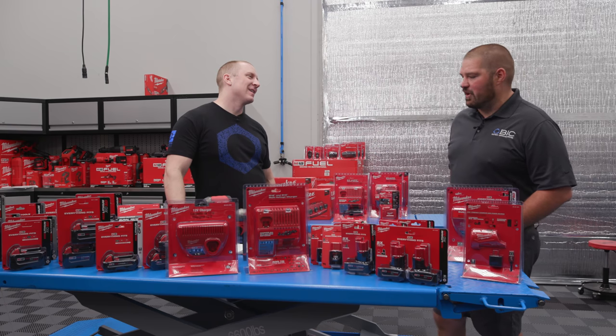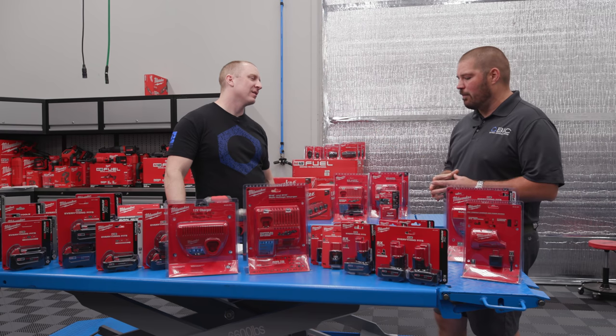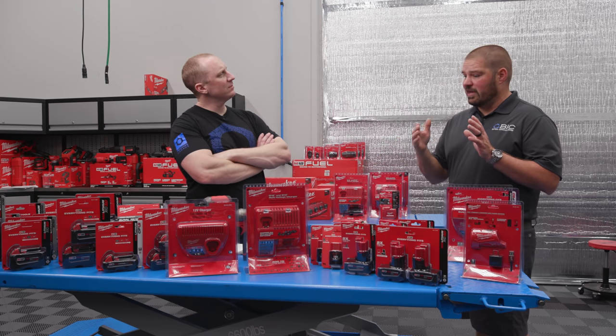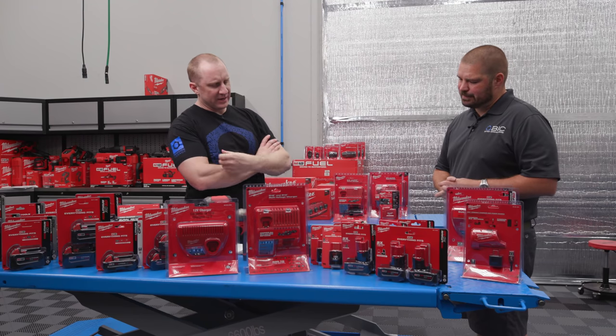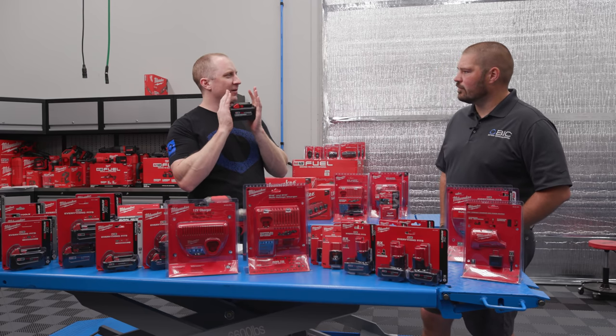Being up at the upper 100% is actually bad — it's better to stay around 30–70%. Hybrid vehicles running lithium-ion do exactly this. Most hybrid buses and trucks that are hybrid-electric don't use zero to 100% — they operate at 30–50%, 30–70%, or 20–60%, staying right in the middle of that range. Is it safe to say the smart battery in the Milwaukee system is taking care of some of that for me by not allowing a complete discharge or complete charge?